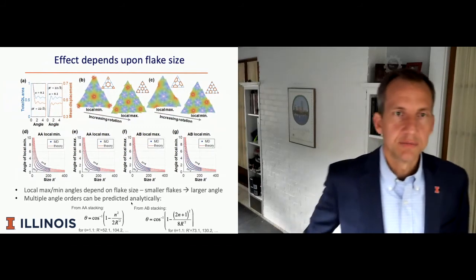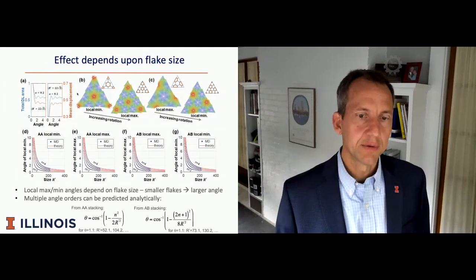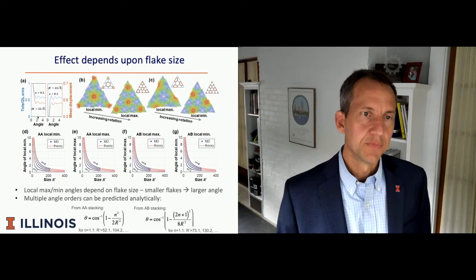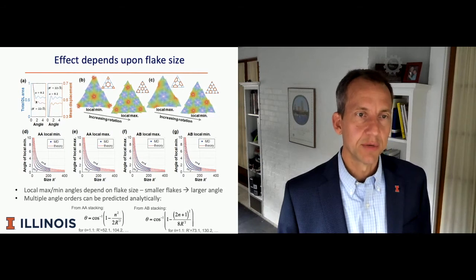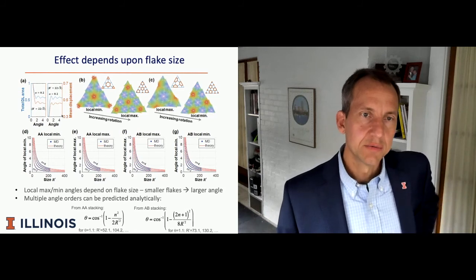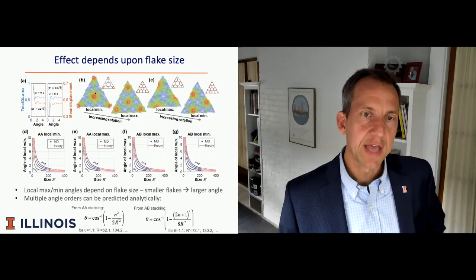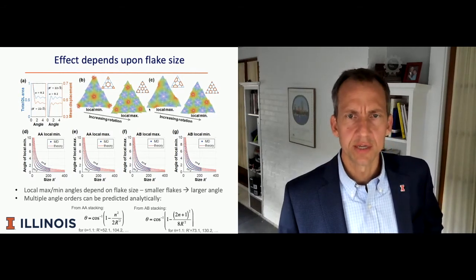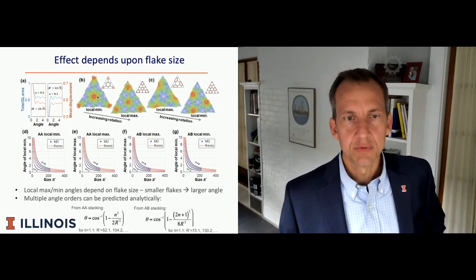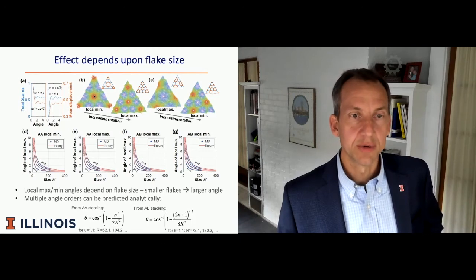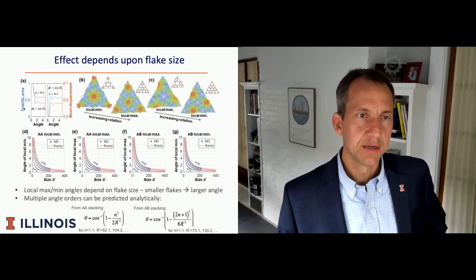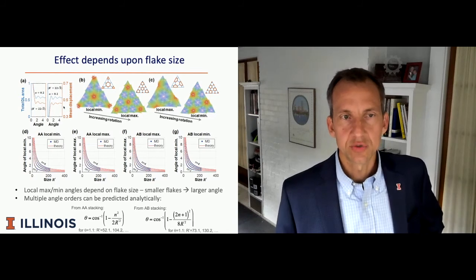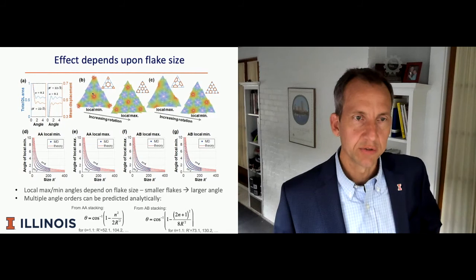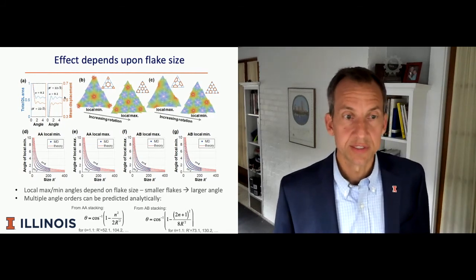We also pointed out that this effect depends upon the flake size. On this slide, I'm showing a couple of things. On the upper left-hand corner, we're mapping the total dislocation line area as a function of angle. Just like we saw with the energy, if we look at the total area of dislocation, we see these local maxima and local minima occurring at discrete angles. We can also associate that with the mean displacement of all the atoms in the crystal. What's shown here in these blue and red triangles represents displacement fields of atoms at different rotation amounts, corresponding to different local minima and local maxima. So whether we think of this as a dislocation line problem or as the strain associated with the displacements of atoms in this rotating triangle, you see the same features that we see in the total energy, which I showed in the previous slide.